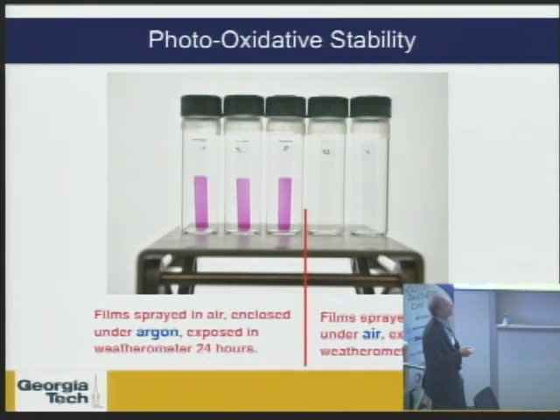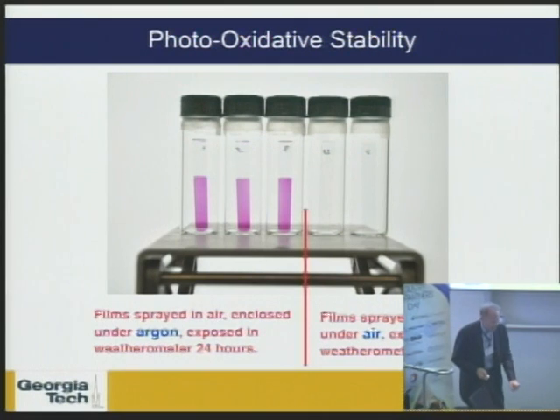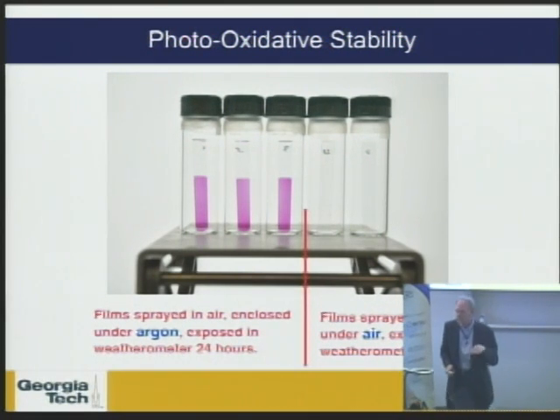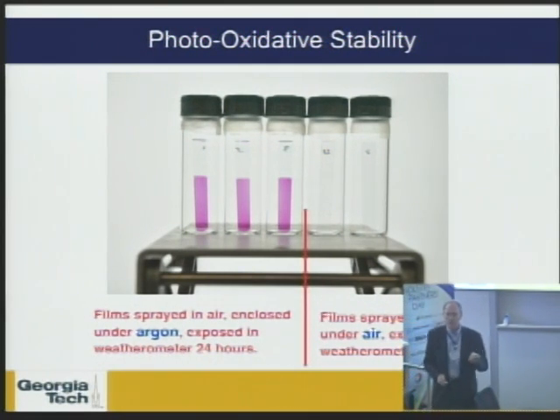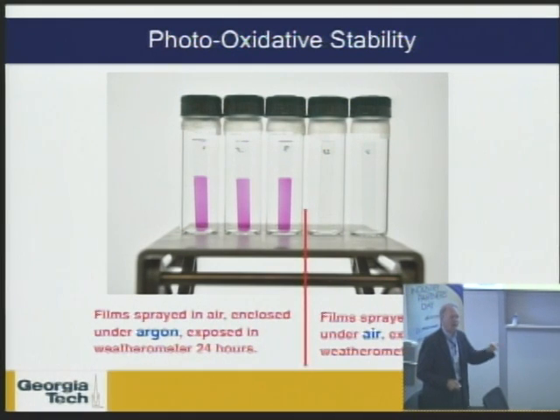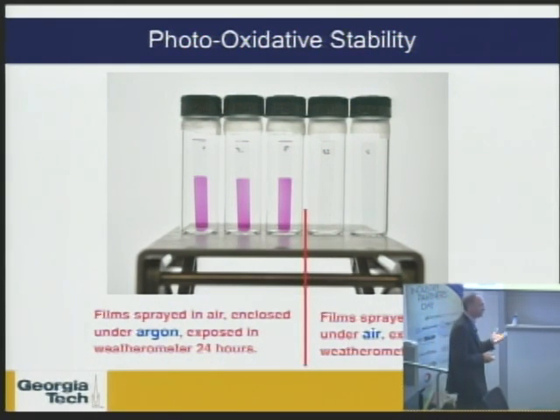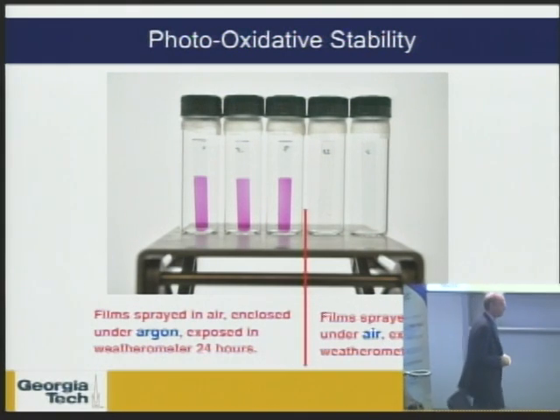And what you can see is that there's photo-oxidation in air. And the point here, and I'll even knock on the table, is yes, this is exactly what's supposed to happen. We make those polymers easy to oxidize on purpose. So if that didn't happen, I'd actually be concerned. But what's nice is that when we do not have oxygen present, the material is very stable. It's stable to color, it's electrochemically stable, it switches, it's electrochromically stable also.